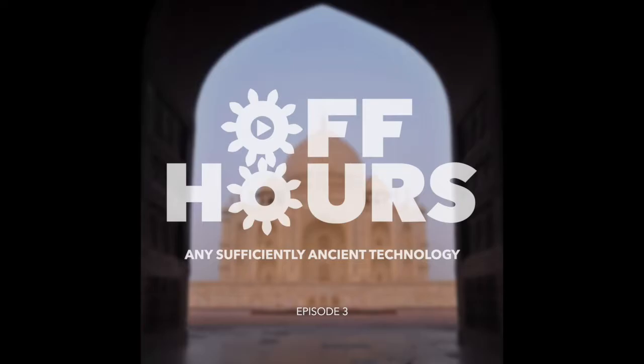5 or 6% shrinkage doesn't sound like a lot, but when you're making parts that interchange with each other, or you're making parts where the pattern is important for it to match up, that 5% shrinkage is quite a bit and can cause problems. Even 1% in watchmaking would be a deal breaker for interchangeable parts. Oh, absolutely. And fortunately, I'm not dealing with parts that require that level of interchangeability. But you're right. And this is one of the reasons why you can't cast a lot of parts for a watch, because the accuracy just isn't there.